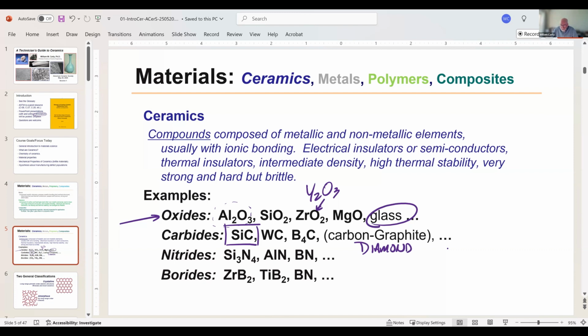Nitrides, silicon nitride is common. I mentioned silicon nitride ball bearings in the first slide, and silicon nitride ball bearings are used in windmills in particular. Aluminum nitride is unique, almost unique among ceramic materials in that it has a high thermal conductivity, but is a good electrical insulator. And the only other material that behaves that way is beryllium oxide, which beryllium has some issues with toxicity that make it undesirable.